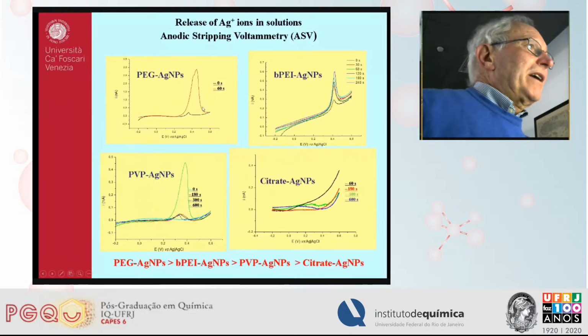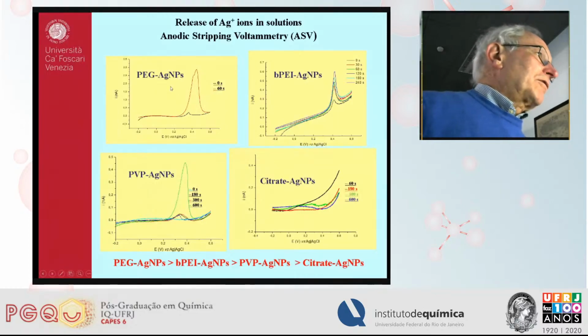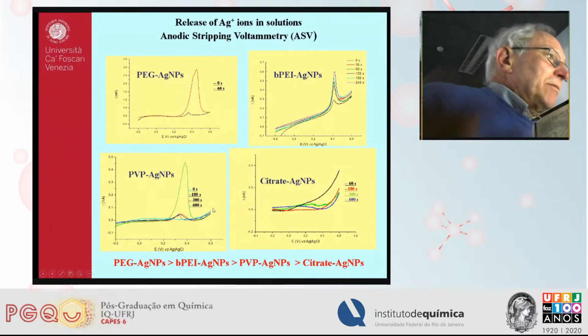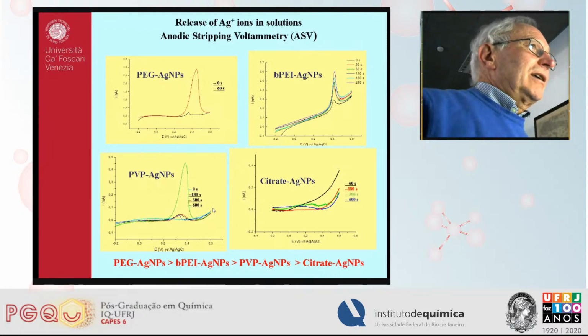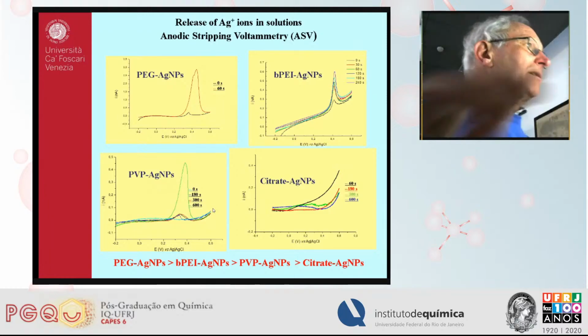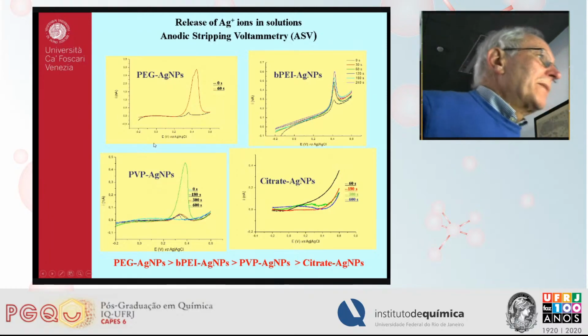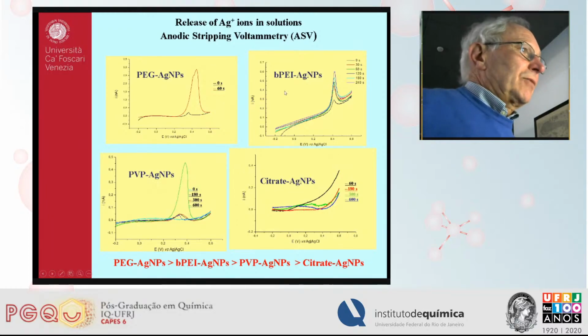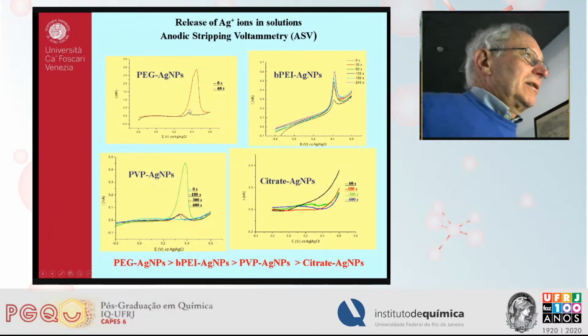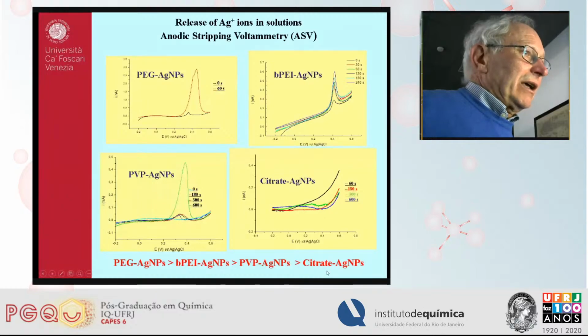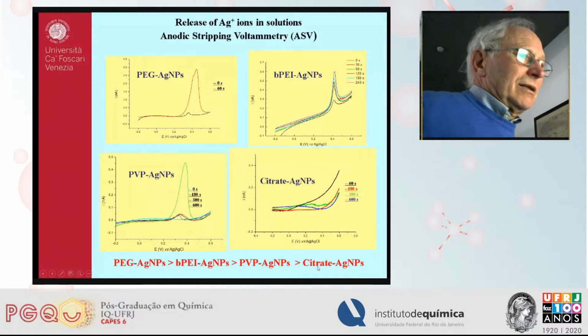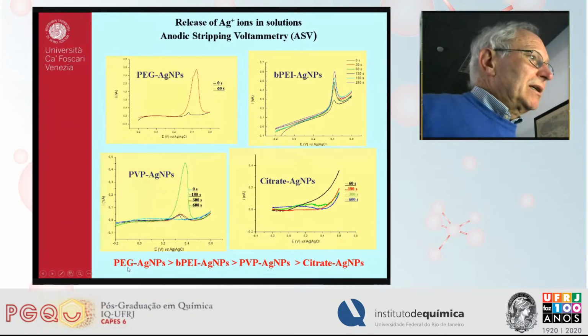This was verified by following the amount of silver ion released with time, and by the parameters we had to use to detect this amount of silver ion released. Here, after analyzing quantitatively the stripping peaks of these four products, we established this scale of reactivity, which indicated that the citrate-coated silver nanoparticle has the least reactivity of the particles, while the PEG-coated silver nanoparticle is more reactive.